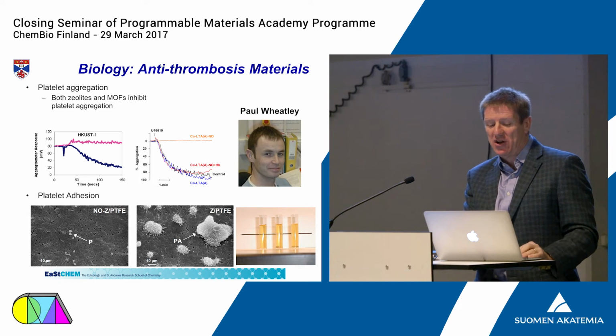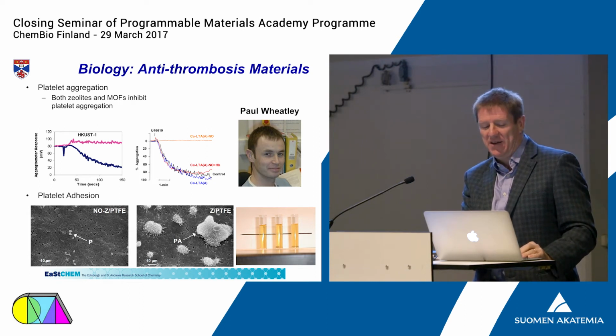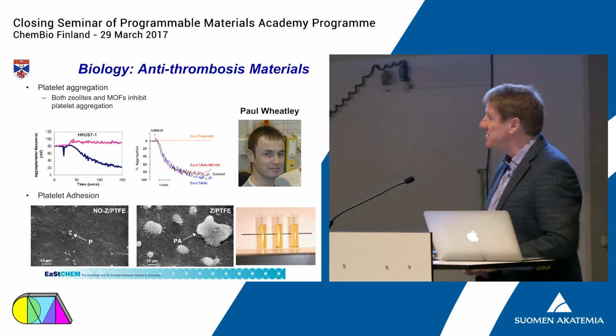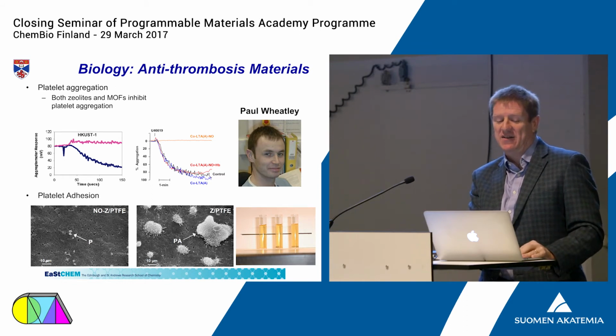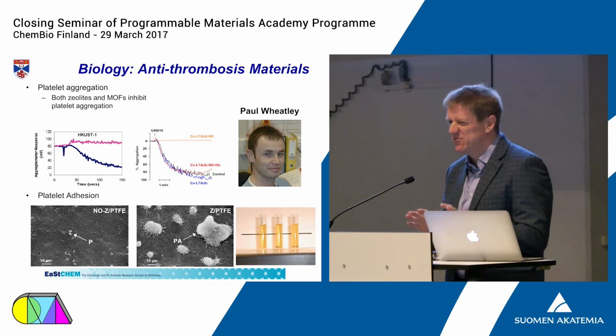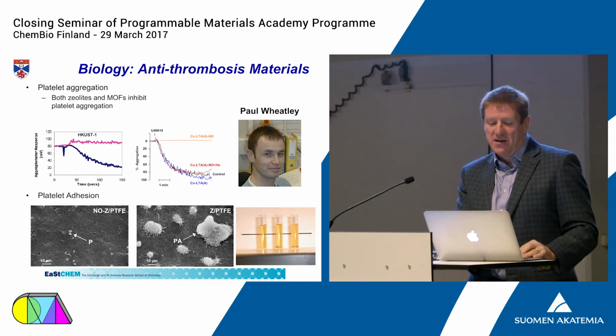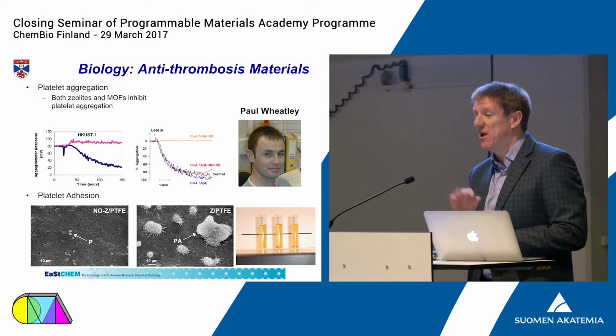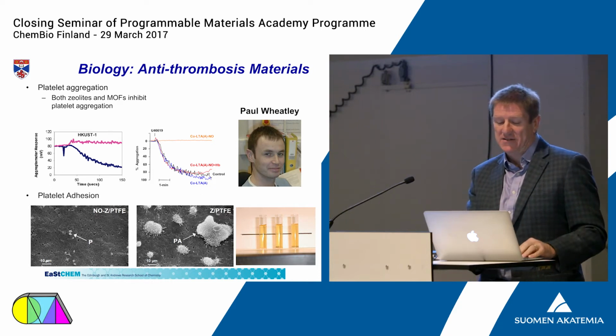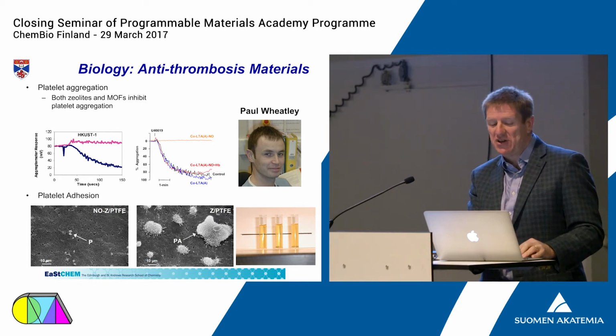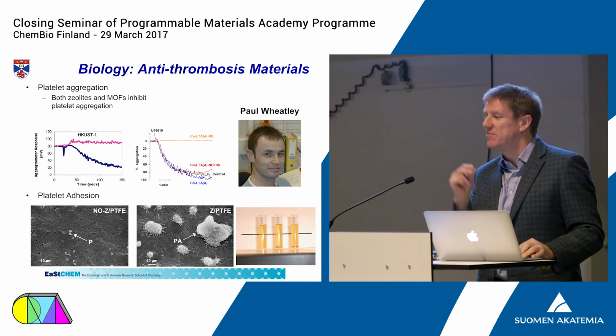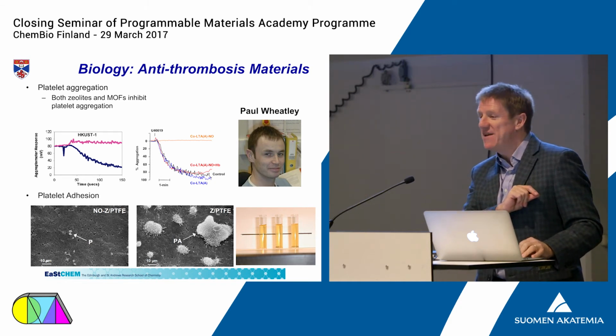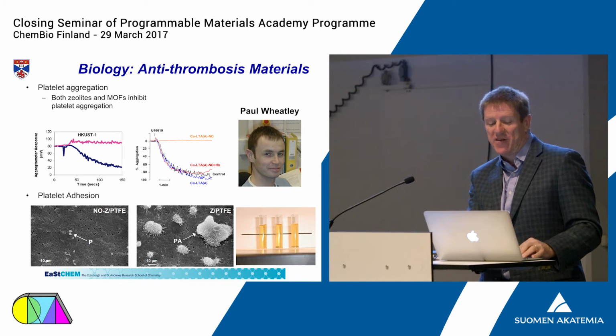So you can actually measure clotting, the extent of clotting, or platelet aggregation, really, by passing light through, which is this experiment at the top here. And these are experiments where we take either a zeolite, this one, or a metal organic framework. It doesn't really matter what they are. And then what normally happens, if you set off clotting, you get a response from the aggregometer. You can pass some light through. Okay? And with that, you can see that the zeolite doesn't do anything. But when it's producing nitric oxide, when it's storing and delivering nitric oxide, it completely switches off the platelets. 100% effective. The metal organic frameworks are just as good too.